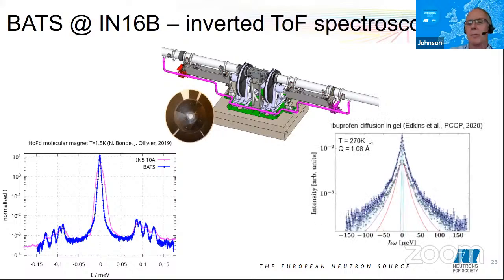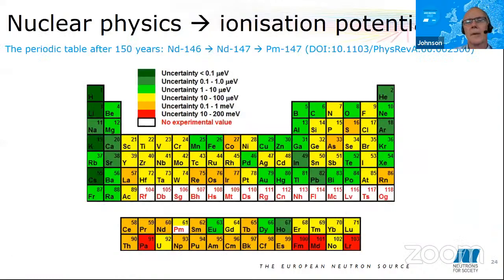And this type of instrument is often used for quasi-elastic scattering, and here's an example that's been published. It's on drug molecule diffusion in gels, and it's by Cathy Edkins from Manchester. So this option on the instrument's used about 30% of the time at the moment, and there's an upgrade ongoing which will allow further improvements here.